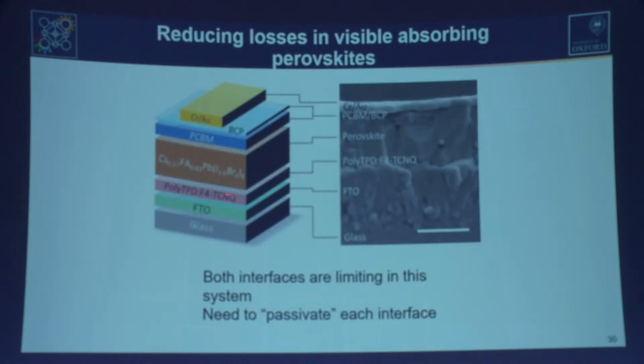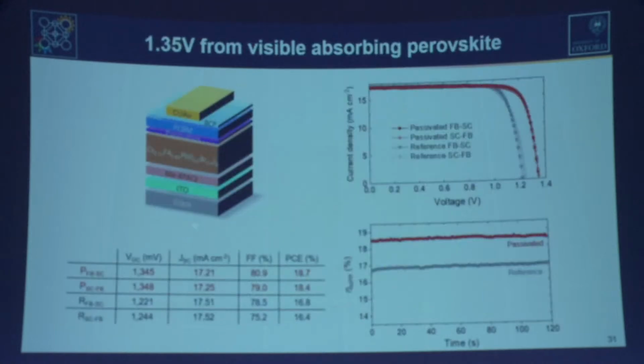This is a schematic diagram of the cell stack, all these different material layers. This one has the p-type, the positive contact on the bottom, negative contact on the top. What we need to do in this solar cell, most of the losses occur between this absorber layer and these contacts. So the losses aren't in the absorber, but basically we have charge trapping at the interface between the absorber and these contacts. So we need to try to introduce some strategies to improve them.